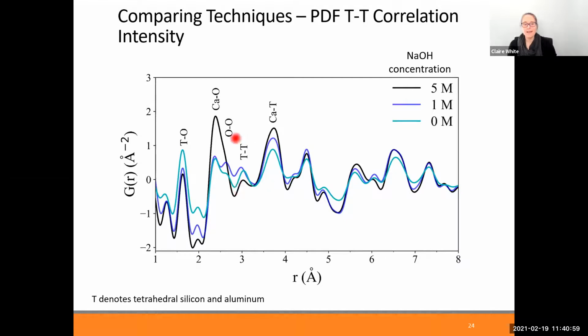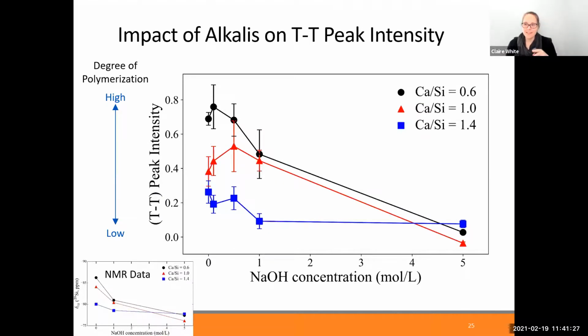The one thing we wondered about here is whether we can use this TT intensity to get a sense of the degree of polymerization of the gel from a pair distribution function. I mean, NMR is the way to go, right? If you want very nice quantitative information on the degree of polymerization for silicates, NMR is the state of the art. But we're interested to see what PDF could tell us about this. So we plotted the intensity of that correlation for all the different samples synthesized under different conditions. And lo and behold, we got very similar behavior to what we saw for the NMR results, which is kind of interesting. Higher degree of polymerization, higher TT peak intensity; lower degree of polymerization, lower TT peak intensity.